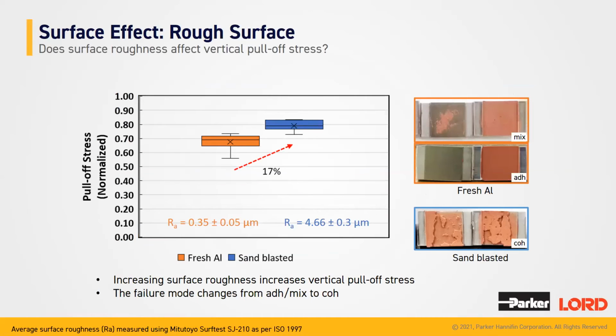So let's start with surface roughness. Here we're comparing the pull-off stress of a smooth surface, which will be the fresh aluminum, and then a rougher surface with sandblasted aluminum. And as you can see, there's a 17% increase in pull-off stress required when moving from the smooth surface to the rougher surface. So we can say that this is a statistically significant difference in the 2 pull-off stresses as determined by a t-test. You can see also that the failure mode changed from mixed and adhesive failure on the fresh aluminum to cohesive failure on the sandblasted aluminum.